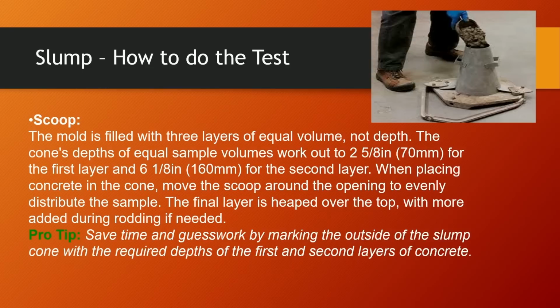Scoop. This is going to be how to do the test. We're going to start with the scoop. The mold is filled in 3 layers of equal volume, not depth. The cone's depth of equal sample volumes works out to about 2 5/8 inches for the first layer, 6 1/8 for the second. When placing concrete in the cone, you move the scoop around the opening to evenly distribute the sample, and the final layer is heaped over the top with more added during rodding if needed.